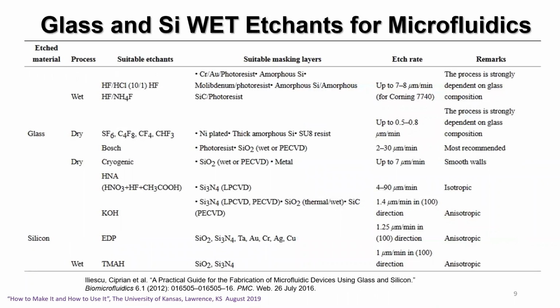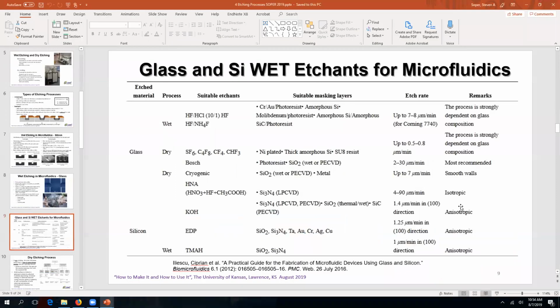Yeah, and thank you, Anish. And look here. I should have mentioned this in more detail. Here's the etch rate for these materials, wet and dry, on a particular substrate, 7 to 8 microns per minute. So that's why this table here is extremely important to provide you that information. Based on my experience, just take those values as rough reference, but never trust them. You have to run